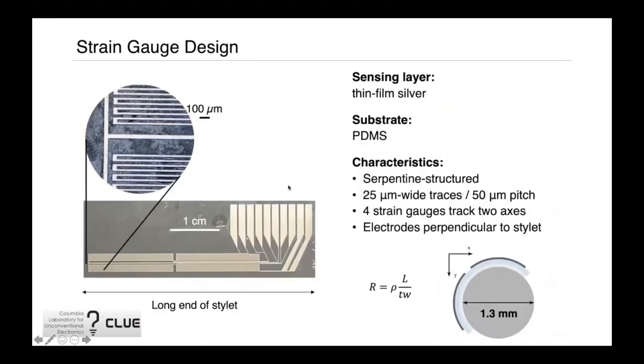Here's our strain gauge sensor design. The sensor consists of patterned thin film silver on PDMS, and the design consists of 4 strain gauges that are serpentine structured to provide a high base resistance in a small surface area. The base resistance is calculated using the equation shown here, where R is the base or unstrained resistance, Rho is the resistivity of thin film silver, L is the total length of the strain gauge trace, T is the thin film thickness, and finally W is the serpentine trace width.